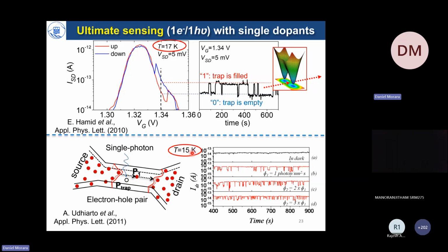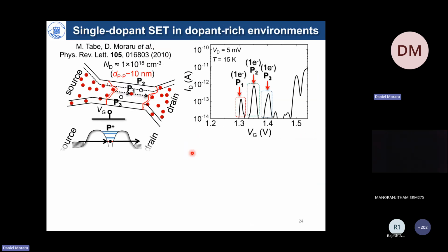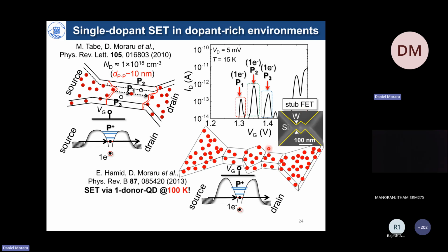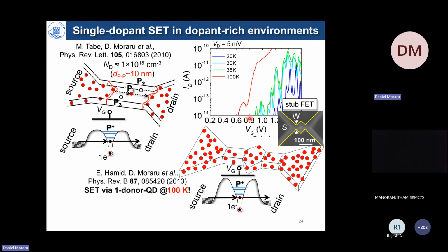But please note that temperatures were relatively low. So now with this kind of background and this kind of physics, we wanted to raise the operation temperature. So to do that, we figured out that we should change the simplistic structure of a channel into a stub-shaped channel. The reason for that was that even if you have a random doping in this kind of devices, some of the dopants could be in these sharp corners and surrounding mostly by SiO2 oxide, and also affected by quantum confinement and dielectric confinement. In that case, the dopant state becomes deeper. So with that, we demonstrated that a single electron tunneling current peak can be observed in some devices even at a temperature of 100 Kelvin, and that was reported as a world record for single dopant devices in 2013 already.